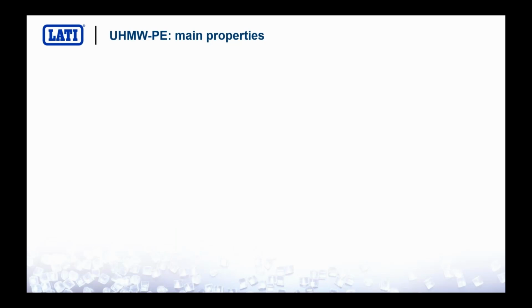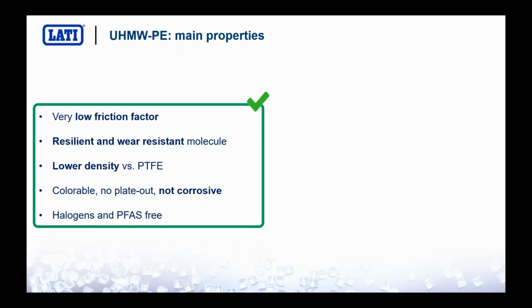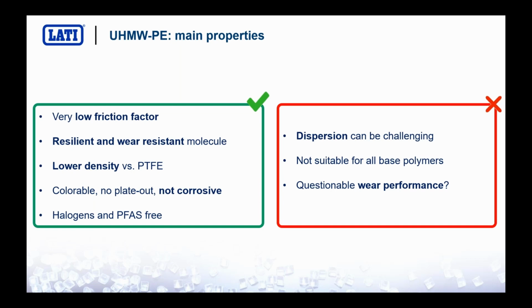But let's move forward. To sum up what ultra-high molecular weight polyethylene is, we can say that the molecule in itself has a very low friction factor, is very resilient and wear resistant. It has a very low density versus PTFE, and a very nice amount of other good properties. It's colorable, does not plate out, is not corrosive, does not contain halogens, and is PFAS free. So a lot of very interesting properties. On the contrary, the disadvantages: dispersion can be really challenging, it is not suitable for all base polymers, and the wear performance up to date has not been as satisfactory as PTFE, but maybe this issue is due to dispersion of the additive or the testing method.